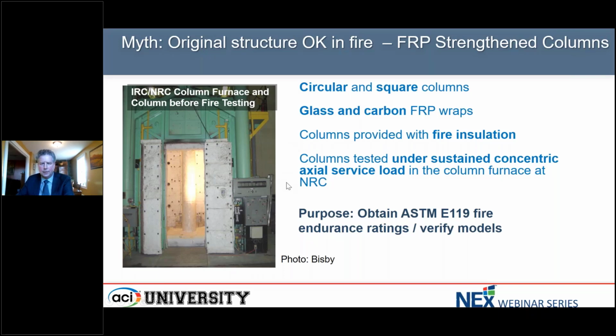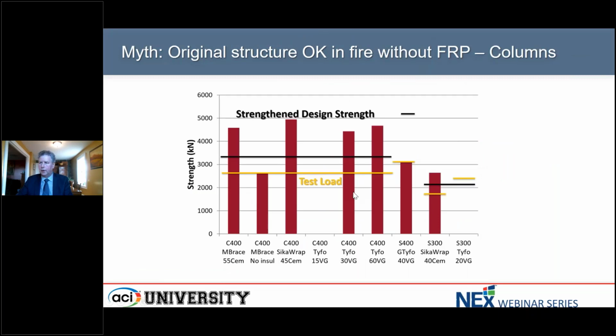We used glass and carbon fiber FRP wraps. We also provided most of those columns with insulation on the outside to provide some fire protection. And then they were tested under axial load, and we wanted to obtain fire endurance ratings, and most of the columns performed very, very well. Most of them achieved a fire resistance of about 4 hours, and you can see in this figure it shows the test load that we had, and then the red bars are generally the amount that the columns actually failed at, when we tested them after the fire exposure.